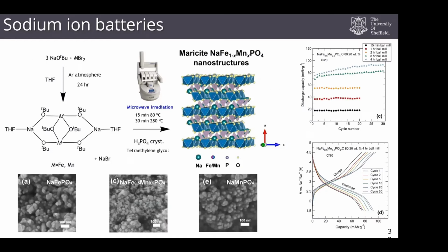I'm not going to go through this in huge detail, but again, it takes about half an hour to make this material. We grind it up for a couple of hours, and we end up with capacity close to theoretical capacity. Theoretical capacity here is about 130 milliamp hours per gram, and we're at about 100 milliamp hours per gram. So we're increasing the performance of these materials by sharpening our synthetic pathway.